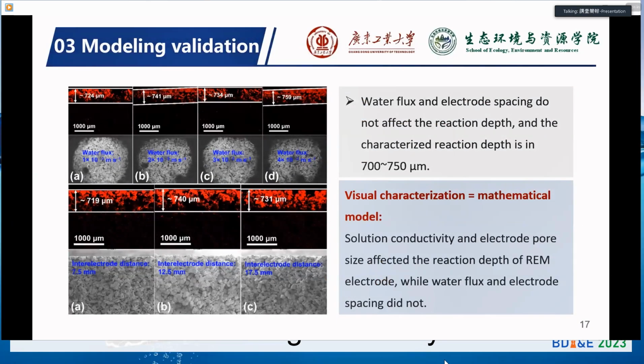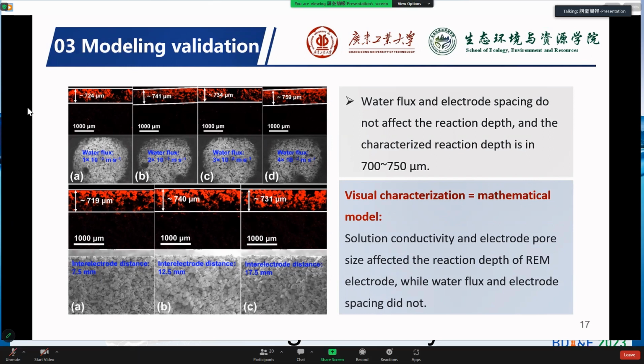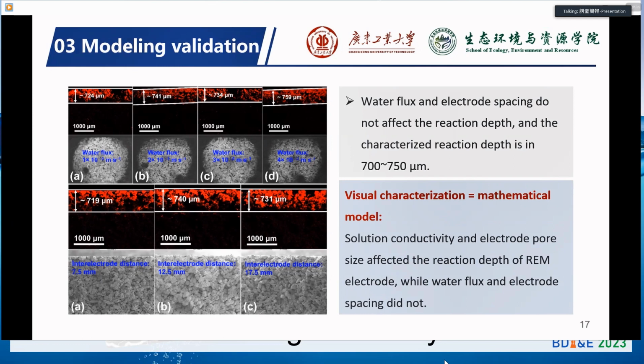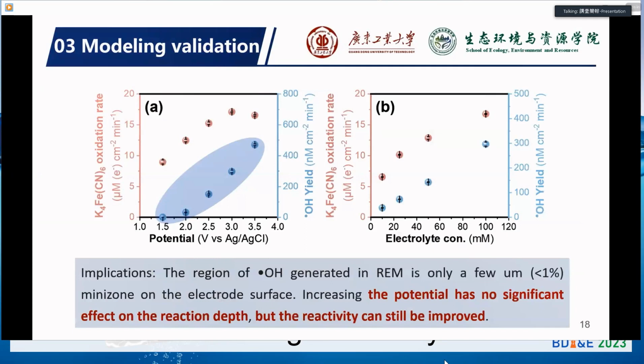According to the visualization results, we find the water flux and the electrode spacing do not affect the reaction depth, and the depth is around 700 to 750 micrometers. The visualization results are also comparable with the mathematical model output. That is, the solution conductivity and the actual pore size significantly affected the reaction depth, while the water flux, the applied potential, and the electrode spacing did not. This should be kept in mind.